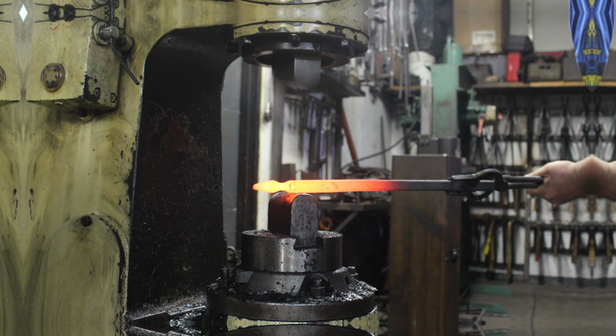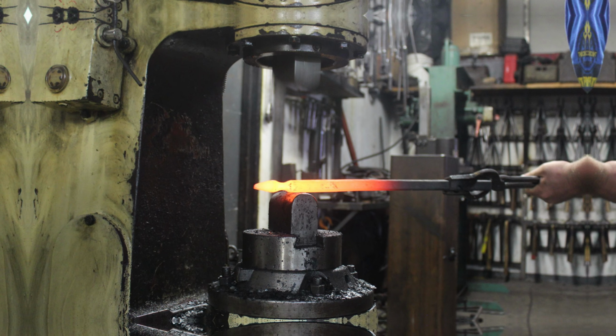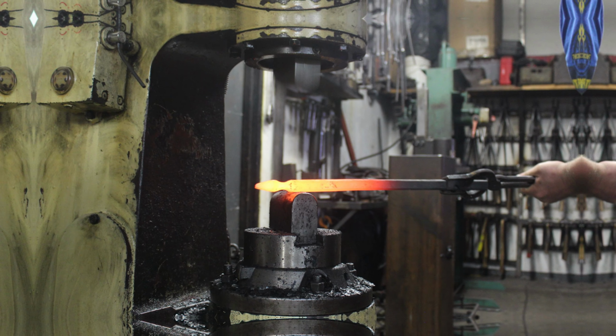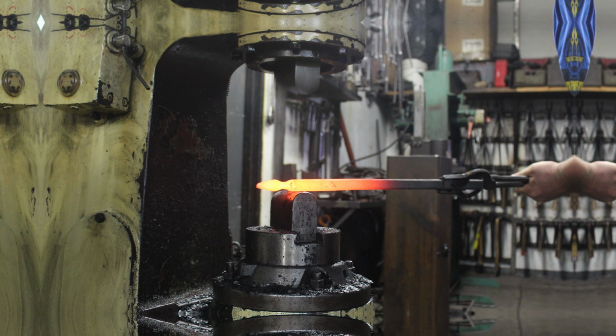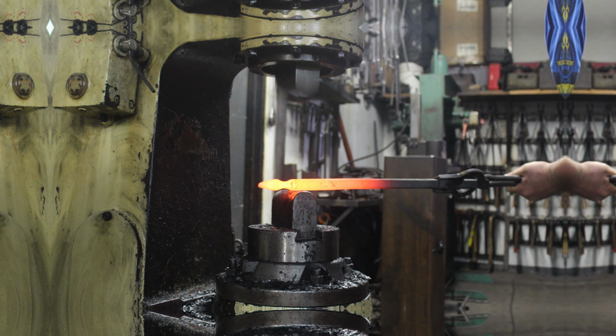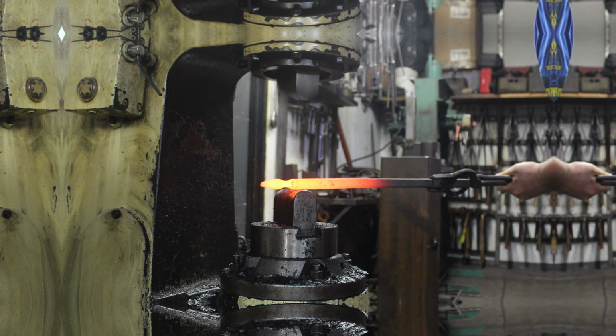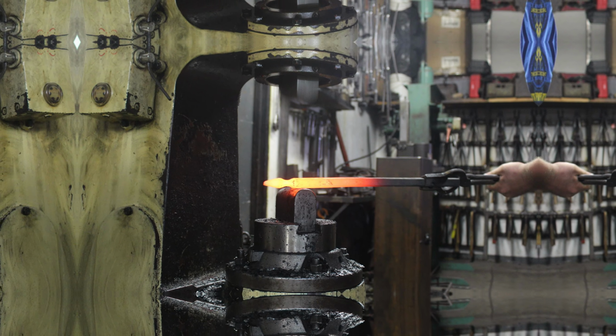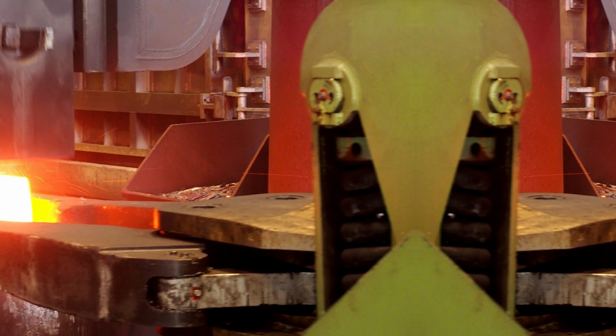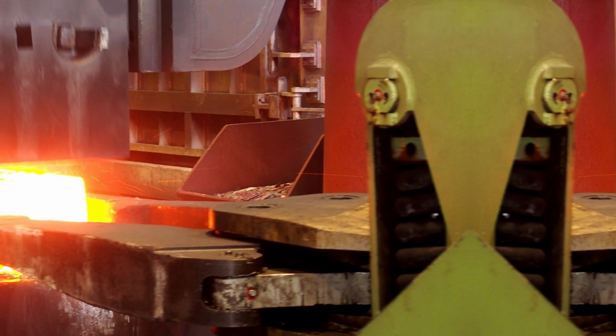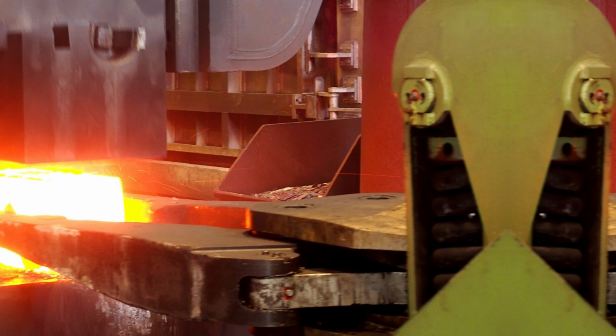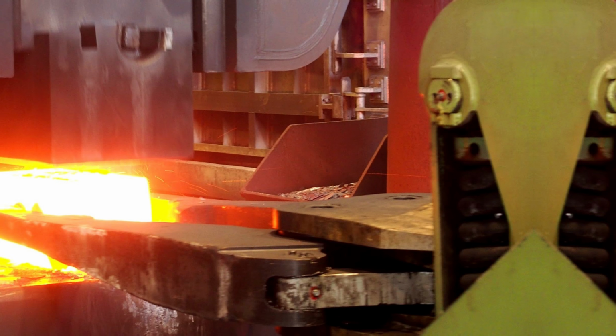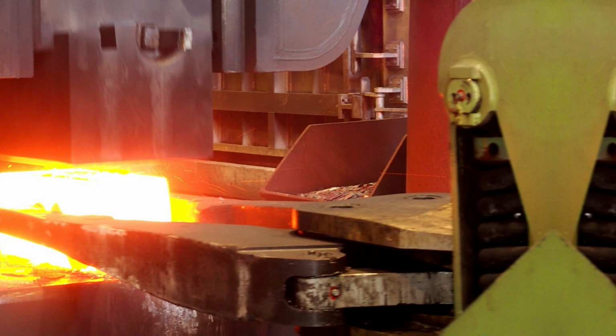Sarah pulled up force time curves from both processes on her laptop. The steam hammer's impact showed a rounded peak that spread force application over 40 milliseconds. The servo press delivered a square wave, maximum force achieved in under 5 milliseconds, and held constant throughout the forming stroke. Mathematically equivalent energy input, but the steel responded to the time signature of force application with dramatically different internal structures.